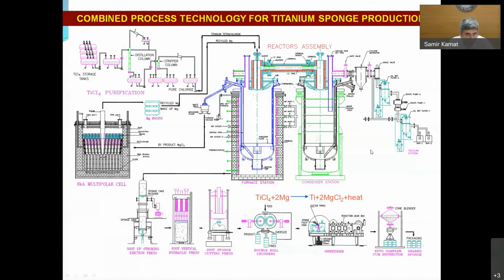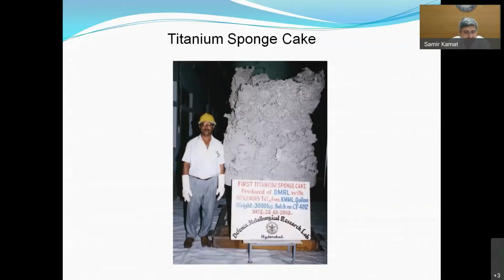I will not go through the details here, but you basically need to first purify the titanium tetrachloride, which was obtained from KMML. Subsequently, this titanium tetrachloride was reacted with magnesium in this reactor to form titanium sponge plus 2 magnesium chloride, which was then recycled to get magnesium from the magnesium chloride, which can then be used again to reduce titanium tetrachloride. So this combined process was established within DMRL after a long effort of about 10 to 15 years. And I think the credit for this goes to Shri R.V. Subramaniam and his team, who started from really scratch and established the entire pilot plant and ran it within DMRL for 3 to 5 years.